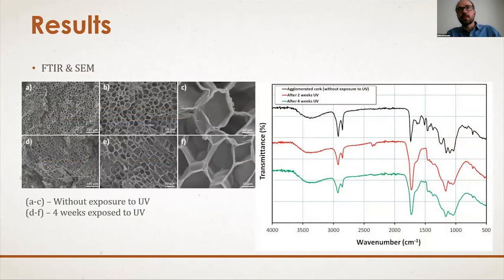And finally, from the FTIR and the SEM analysis, in order to check for possible changes in the characteristics of the samples and also changes in its morphology. So the SEM micrographs show clear microstructural changes caused by UV radiation. So we can see that there is some irregularity and collapse of cork cell walls.